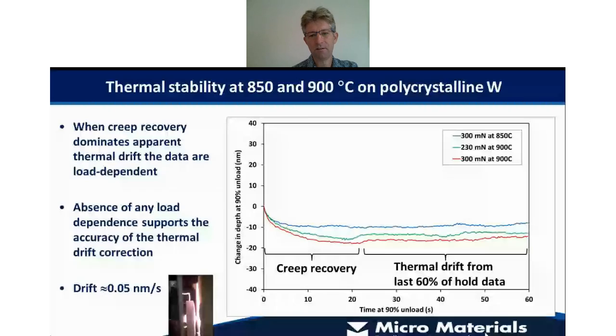So if you look in this graphic here, in the first 20 seconds or so, we're getting a fairly quick depth change, and that's down to the creep recovery in the material. So we're seeing that is lower at lower temperature, and it also increases at the higher temperature. This is exactly what you expect from a materials effect. But if you look at the last part, the last 60 seconds, you can see that's independent of the loading history and actual test temperature. And that gives you a lot of confidence that the thermal drift is minimized in these conditions.